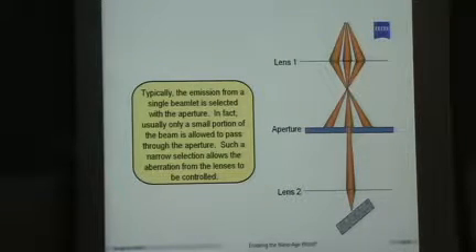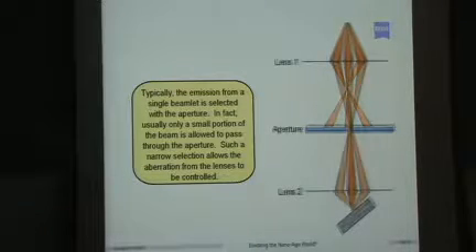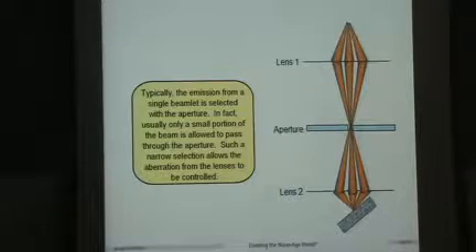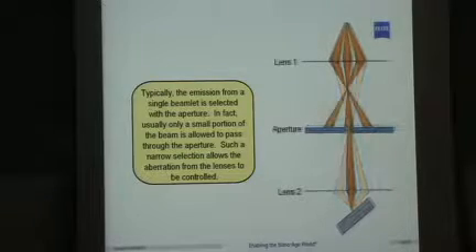So of those 3 beamlets that are coming out, we tend to focus them through that first lens 1. They pass through an aperture that stops the other 2 beams. Yes, we're completely wasting 2/3 of our helium. And then the remaining part that comes down, we focus. We can also change the focus parameter so all of the beams go down. This gives you a bigger spot, but it gives you 3 times the current. Typically, for highest resolution, we send 1 atom's worth of helium beams down, like this.